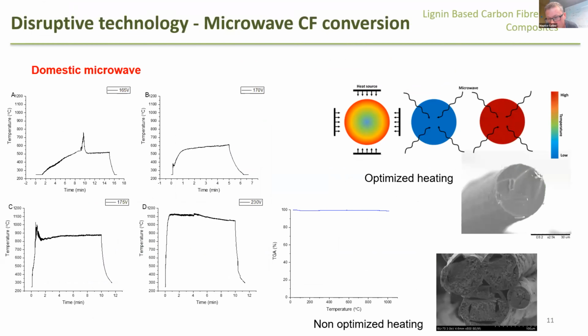Just a few words on that. This is a disruptive technology that we've developed here at Limerick, where we can produce carbon fibers using a microwave. It works for lignin and for PAN, so it works for traditional carbon fiber precursors as well. If you put a PAN precursor fiber into a microwave and you turn it on, nothing will happen. It doesn't absorb microwave, neither will lignin. So what we did is we put a little susceptor coating on the surface of the fibers. When you turn on the microwave, it then heats up and carbonizes. We control the power on the microwave, and by controlling the power, you can control the heat. You can see here that we were able to reach temperatures of over 1,000 degrees C. So we're able to produce carbon fiber.